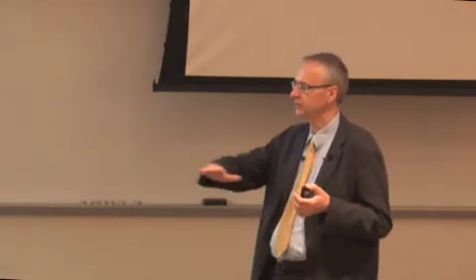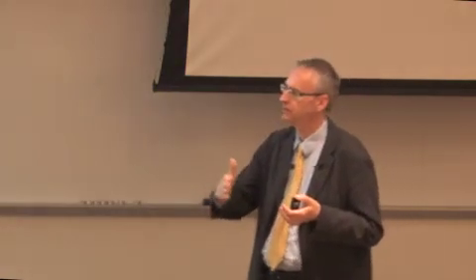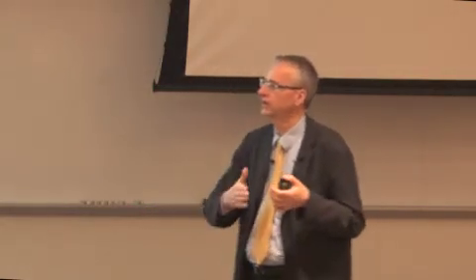Karl, can you comment on the deposition rates and how they impact your cost analysis in terms of the manufacturing? Yeah, we did some estimates, and the very simple message is if you do a roll-to-roll production, you have a tool depreciation range for slow speeds and a material limit for higher speeds. When you are above about a meter per minute, you get into the materials cost limit. At the moment, we have reached rates of about 1 meter per minute, and I would personally expect that in long-term production we will be at several meters per minute. Then the tool cost is a few percent, and the materials cost dominates the production cost.